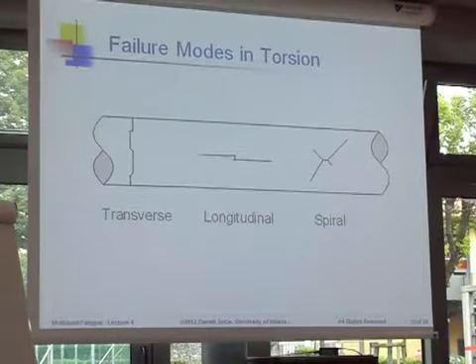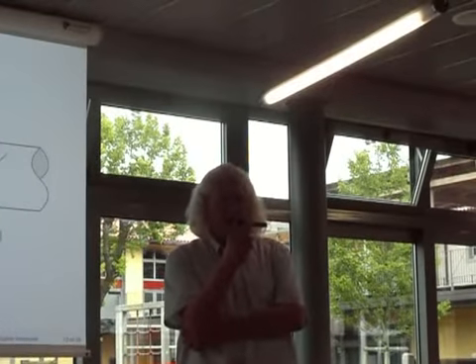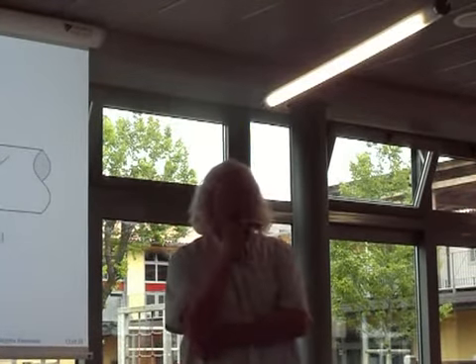And the first thing to note is that if you give me a bar that has been tested in torsion, then I will tell you what the fatigue life is, just from the broken bar. How can I do that? You know, shear loading is unique in that depending on the lifetime, you get very different fracture modes.